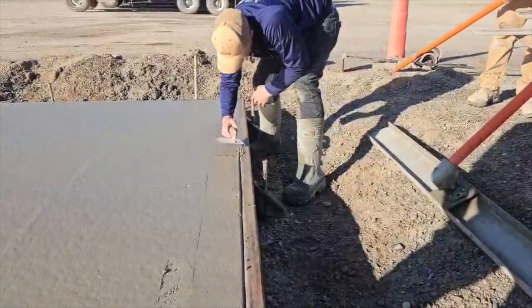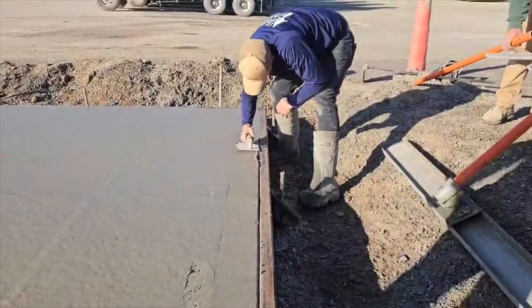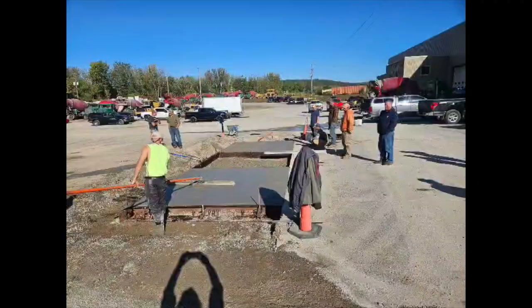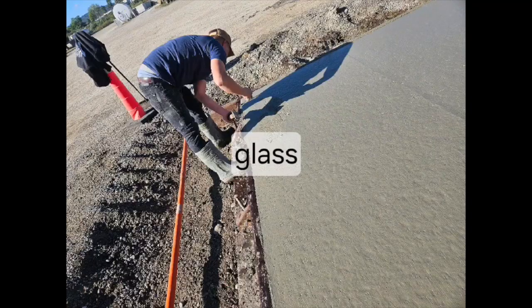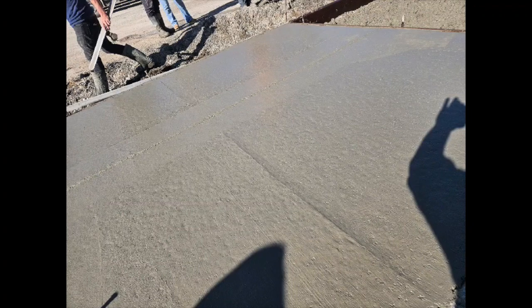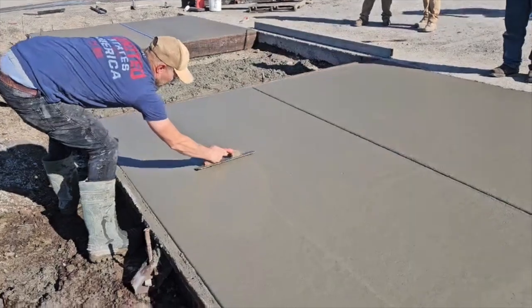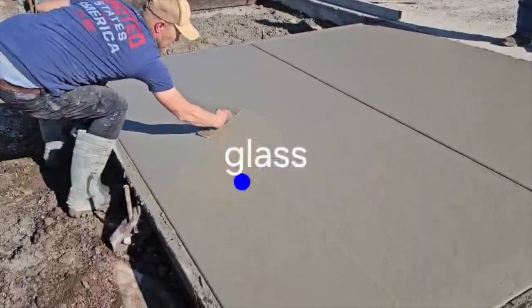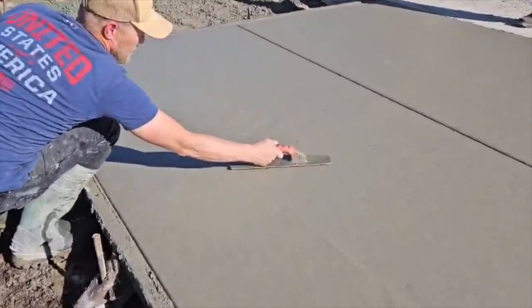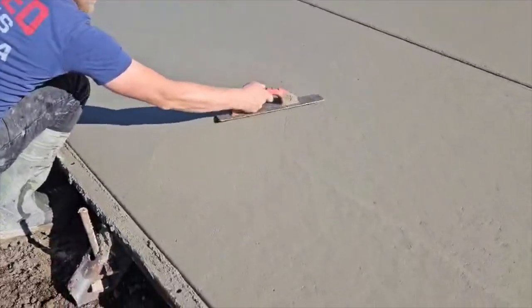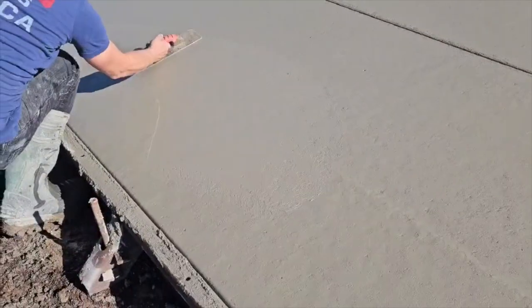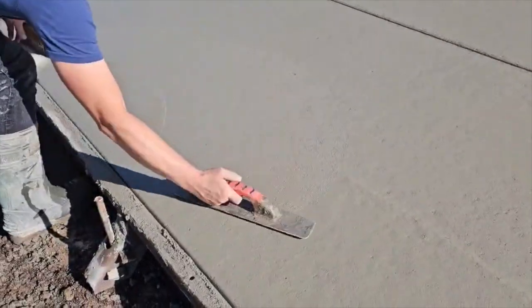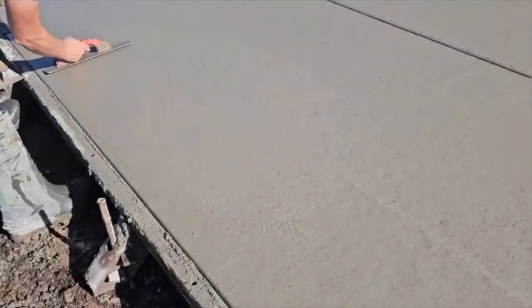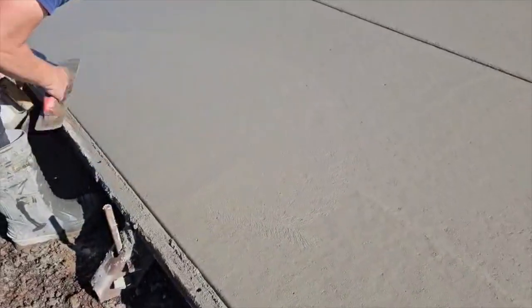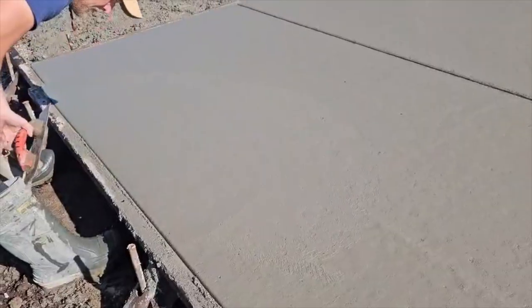The second product we tried was recycled glass, which is newer to the scene, but performs much like slag, with maybe a little less water demand and a little bit higher strengths. Both products cut back on the total amount of cement used, which is very helpful in the industry's efforts to reduce carbon emissions. Both products, the glass and the slag, will also slow the heat of hydration, which is a benefit to finishing on hot days, but not so much in strength gain on cold days.